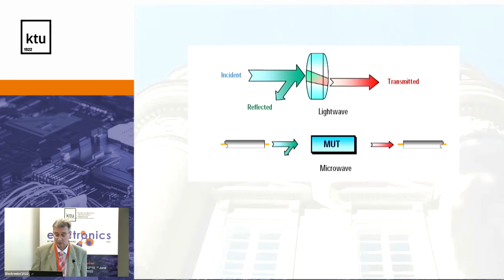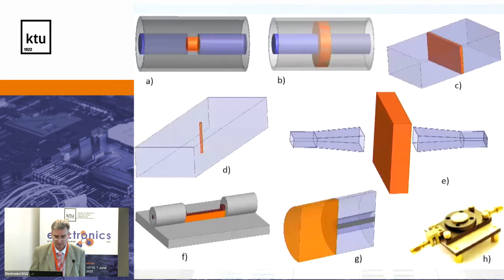So material under test, incident microwaves or electromagnetic wave, reflected, transmitted, and to calculate, then we should go back to Maxwell equations. And Maxwell equations are, as I already mentioned, true, they are working, but you have different boundary conditions, very different. So there are a lot of methods which are used to extract the parameters of the material in different configurations. So here in A, you have a coaxial line, inner conductor, outer conductor, and material under test, which you can place in the middle of the coaxial line. And then measure, again, reflection and transmission.